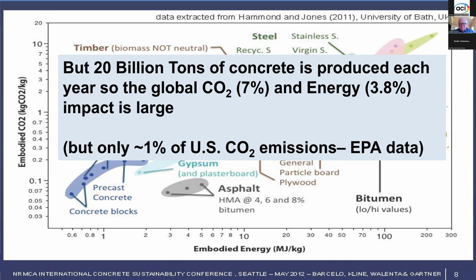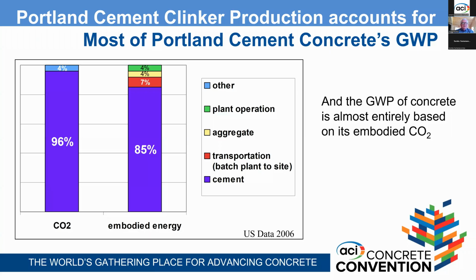China produces more cement in 2 or 3 years than the US did in 100 years. So it's a different scale. But again, Portland cement is just one part of the concrete. If you look at this concrete data, about 96% of the CO2 coming from concrete is coming from the cement, the dark blue. And about 85% of the embodied energy is also from the cement, if you're only using Portland cement concrete.